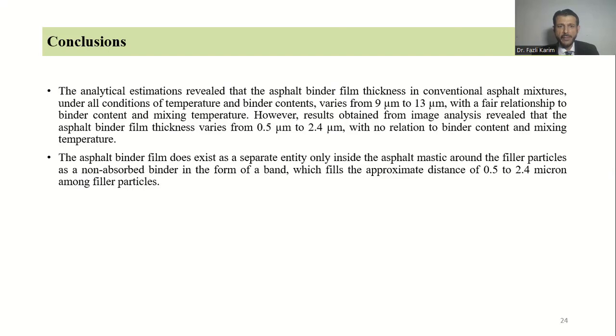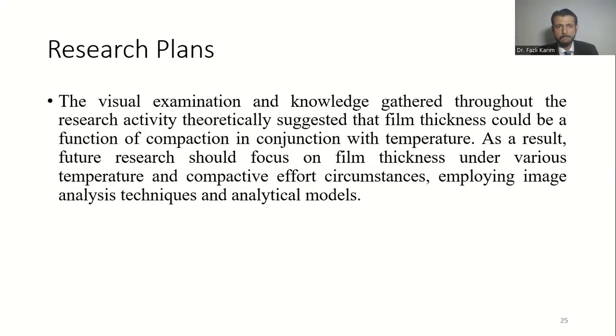The asphalt binder film does exist as a separate entity only inside the asphalt mastic around the filler particles, as a non-absorbed binder in the form of a band which fills the approximate distance of 0.5 to 2.4 micron among filler particles. So these were some of the findings.